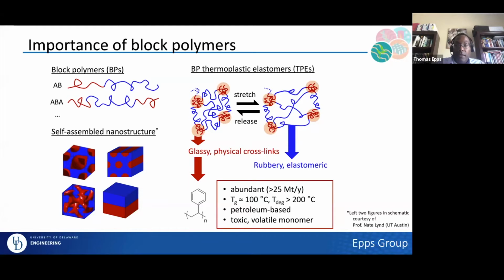Now, one of the things that I can think about, again, I'm going to focus on the red here in the talk, is that if we have, say, a polystyrene, relatively abundant as we talked about, glass transition temperature right at about 100 degrees, and that's right at about the use temperature for many polystyrene-based materials. For those of you who are not quite familiar with what that means, think about your styrofoam cup and adding boiling water to it. That's about the temperature where that cup becomes quite soft, and that softening temperature is very close to a glass transition temperature for the material.